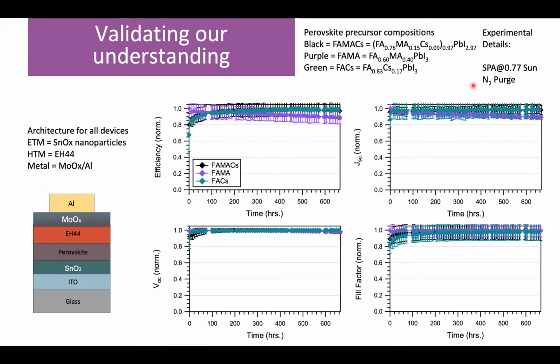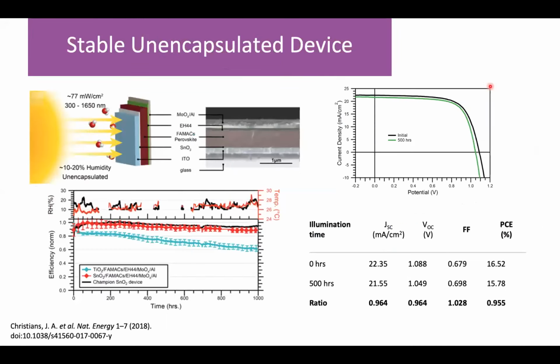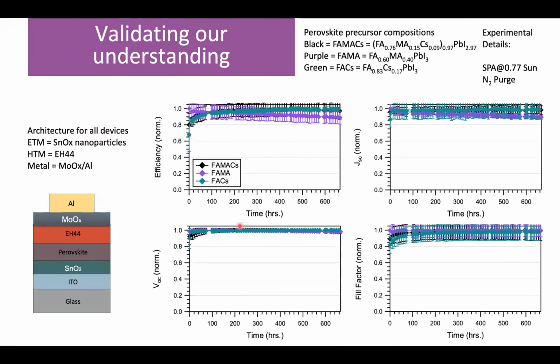Here, we are basically keeping water and oxygen out, which are known degradation mechanisms, in contrast to this data where we let water and oxygen kind of have at the active layer, which is a known source of degradation. So we were really able to do this quite well.